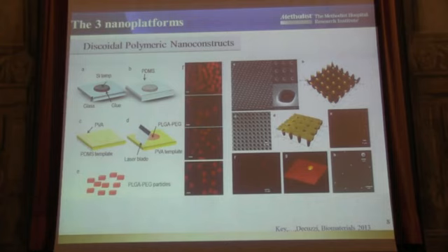In this case, these are PLGA-PEGs, so hydrophobic and hydrophilic chains that are entangled together. And they come in different sizes and shapes, and we use basically a combination of electron beam lithography techniques, so classical microfabrication techniques, or nanofabrication techniques if you want, combined with polymer chemistry and classical polymeric nanoparticle synthesis.